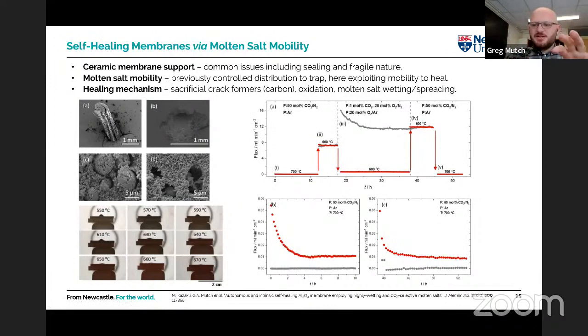So this membrane leaks. It doesn't work after this. But if we take the membrane through various stages of temperature, we can control the spreading of the molten salt, and it essentially acts like a sealant. The molten salt will move and reseal the membrane in a similar way to how your bones will heal over time if they're given time.